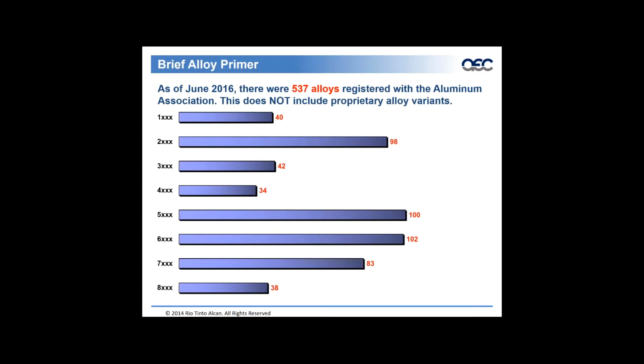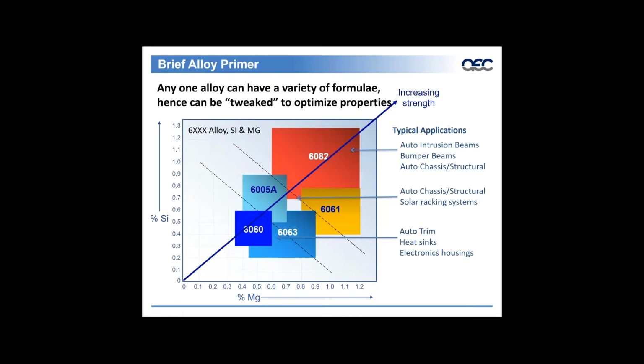As of June 2016, there were 537 alloys registered with the Aluminum Association. And this is a key note: that does not include proprietary alloy variants, and that's considerable. You can see here in the 6000 series there were 102 at that time. The purpose for that is the ability to tweak an alloy and tweak a chemistry specific to the needs required for the application, whether that be grain structure, performance, or mechanical properties. As of 2016, 102 within the 6000 series, 83 within the 7000 series, and 42 within the 3000 series. Again, this does not include proprietary alloys specific to an application.